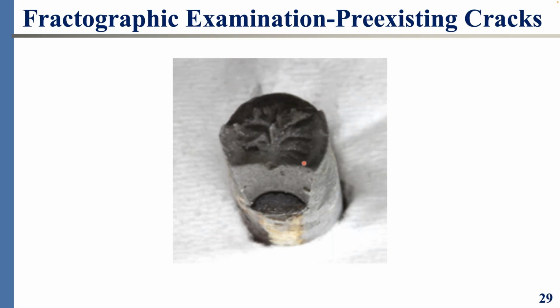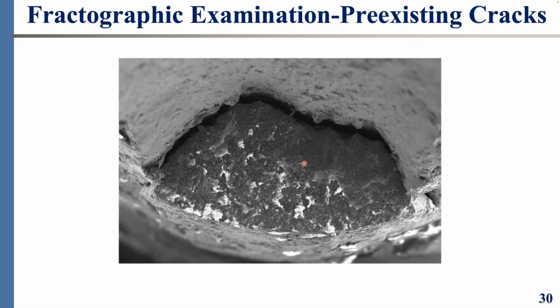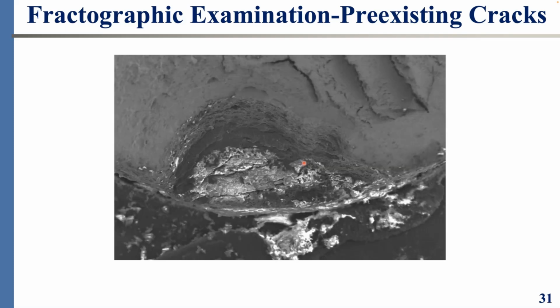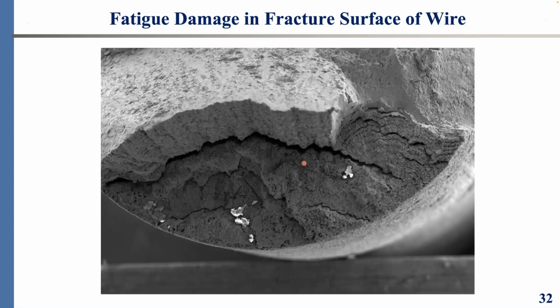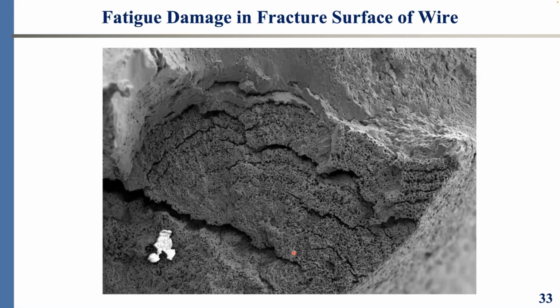So here is another demonstration of these wires. This kind of wealth of information is invaluable in the analysis of the cable strength, in the forecast of life, and in the assessment of degradation. Over here, we see fatigue damage in this cross section. Again, this is a circular shape. I'm coming here to the surface and just the crescent part or the thumbnail. And if we zoom in on the area where it shows vivid fatigue beach marks that could be quantified, and we quantify that to determine the life of that bridge wire when it was taken out of the bridge cable with very high level of precision and accuracy. So now I kept saying embrittlement.